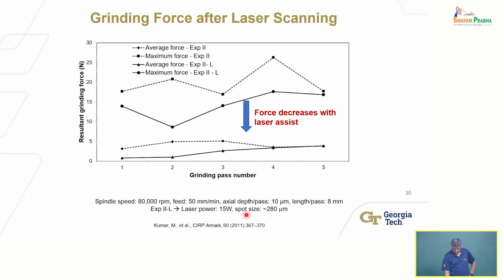But laser power of 15 watts, spot size of 280 microns. And you can see here that there's a number of grinding passes, okay? Because you can't remove all of this in one pass. Because some region is amorphized, it's very weak, but you want to produce a 30 micron depth. Below that, it's weakened, cracked, but not completely amorphized to just fall off. It requires some force to remove.